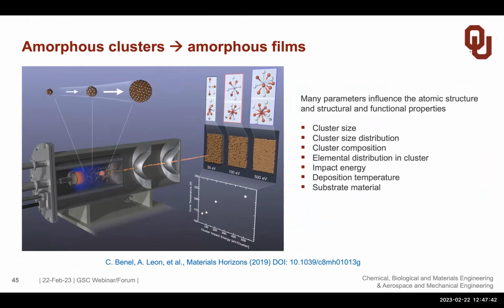But here we produce the clusters and you form a beam, and this just doesn't show the details of it, but we can now deposit the clusters, identical clusters at 50 eV per cluster, 100 eV per cluster, or 500 eV per cluster. And now we studied using a technique called EXAFS, extended X-ray absorption fine structure. We can study the structure, and we see that the structure changes as a function of deposition energy.